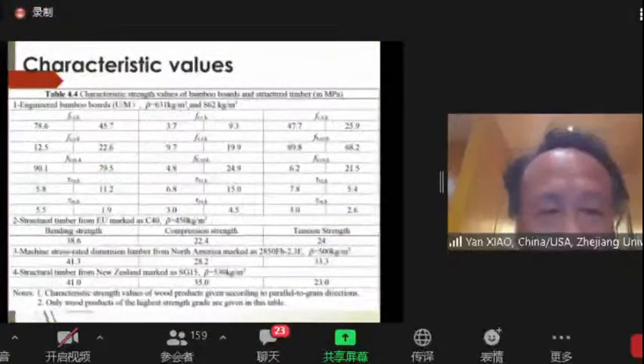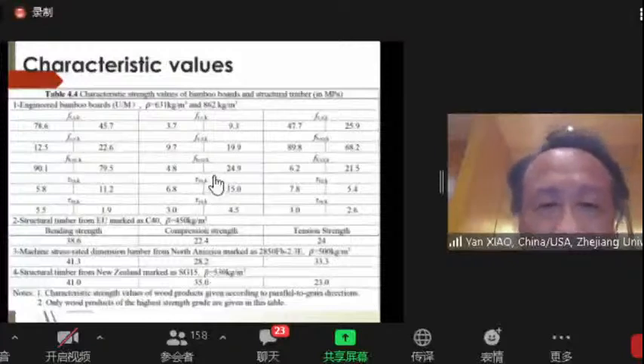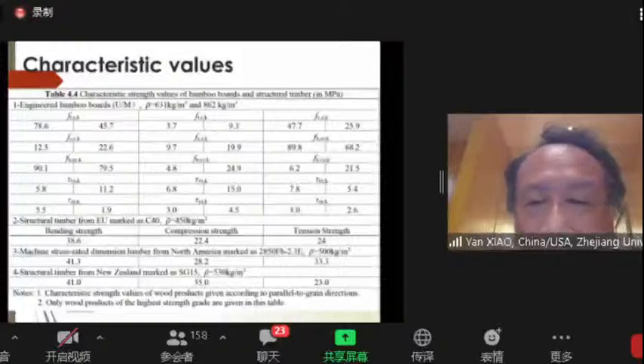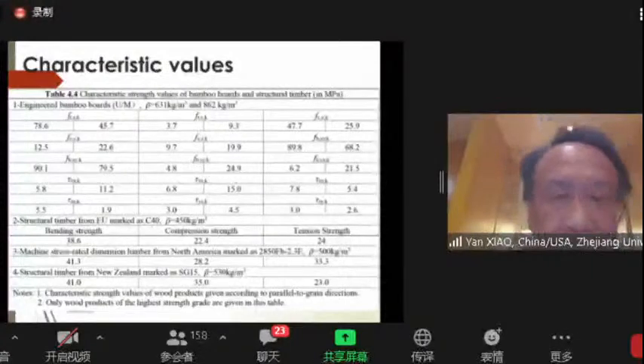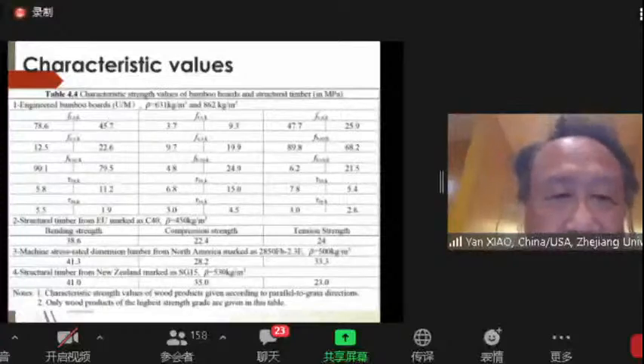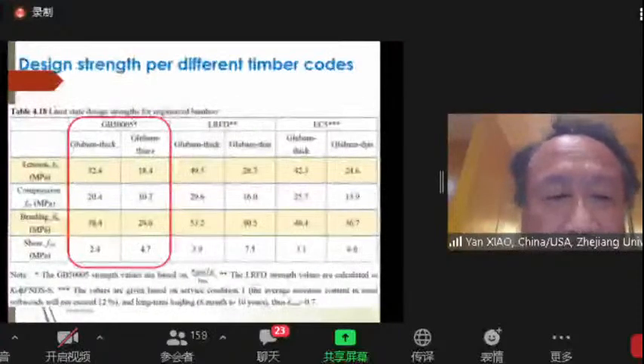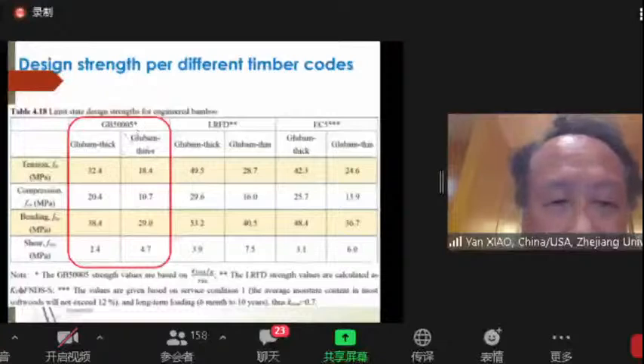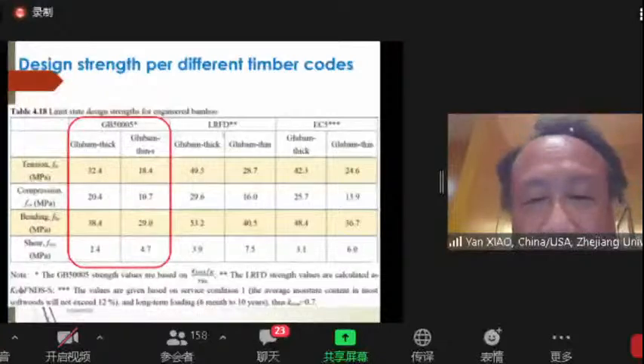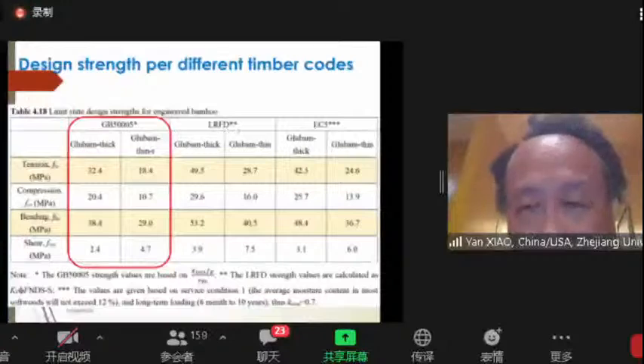Then we conducted a tremendous amount of material testing because at the moment we don't have a code or standards. So we basically follow the testing standards for timber to obtain the material strengths. First of all, we obtain the characteristic values. And based on the characteristic values, we referenced different codes, for example, the Chinese code, the US LRFD code, and the European EC code 5.